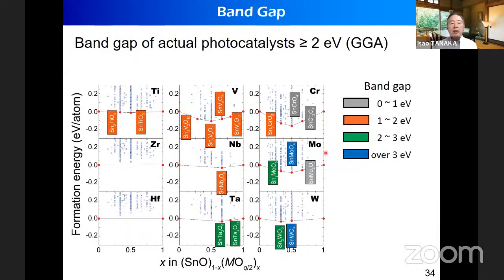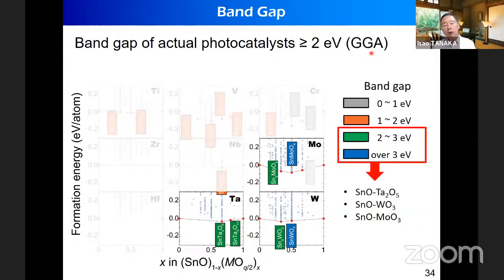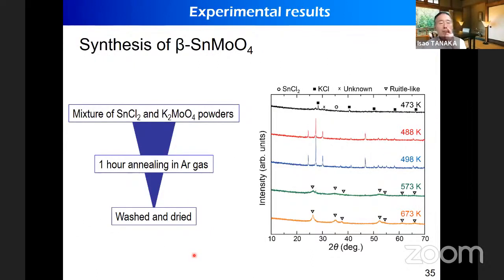But we are interested in visible light photocatalysts. So it should exceed at least the band gap of 2 eV by GGA calculation. So we can filter out those materials with narrow band gap, and we will focus on the remaining compounds. Among them, we focused on tin molybdenum oxide, and in a lab, we did an experiment trying to synthesize this new compound.